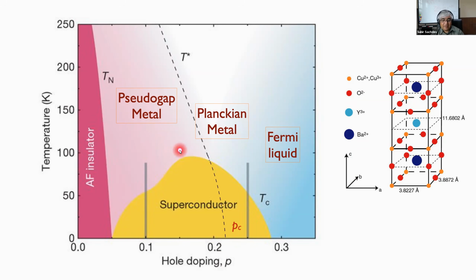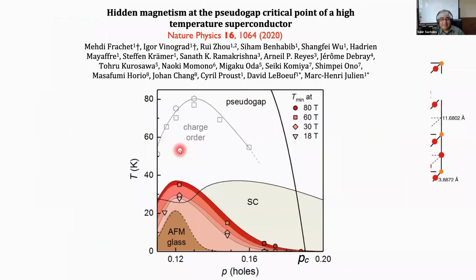Okay. However, I'll just show one experimental plot of this is NMR data from last year from the group in Paris. And what they see by measuring NMR is that previously there'd been some detection of glassy spin-like behavior where the spins freeze into static configurations. I'll talk about this a bit more later. But what they found when you applied a magnetic field, that this glassy behavior extended all the way to PC. So this spin glass type behavior is something that's present in the pseudogap regime. It's an important characteristic of the pseudogap. Okay, so that's the title of their paper. Up to the critical point, you see this hidden magnetism.